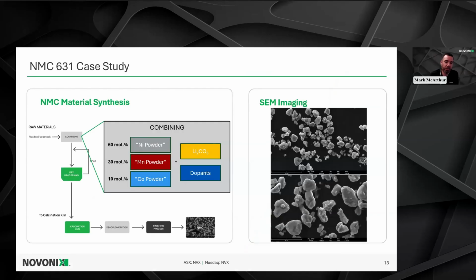So we initially began this journey tackling a mid-nickel chemistry. We thought it would be an easy first step to demonstrate that the process works on a topical cathode chemistry. And what we initially began with was an NMC 631 product. This is a 60% nickel material where we combined, as I show on this slide, 60% nickel powder to 30% manganese powder, 10% cobalt powder, together with lithium carbonate and dopants all in a single step. And that combination of materials underwent the all-dry zero waste process.